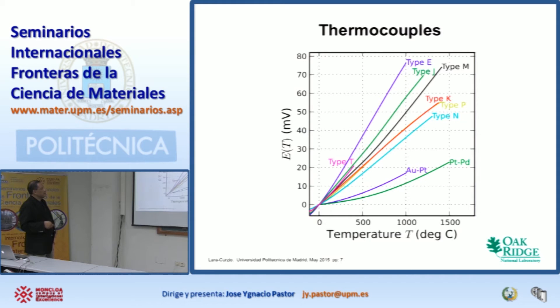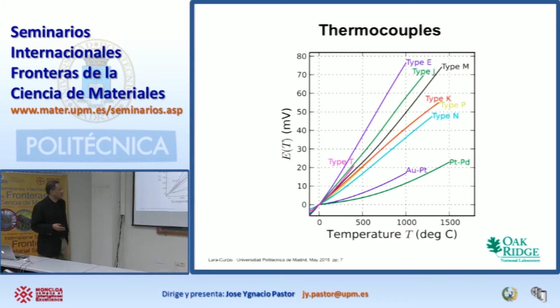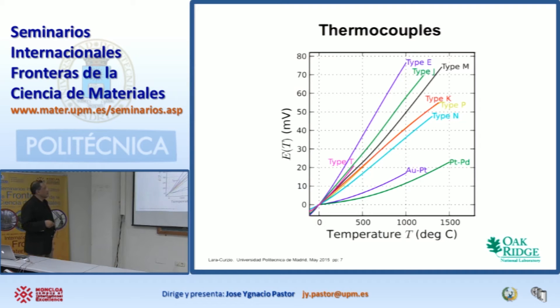We used to do a lot of work with ceramic matrix composites taken up to 1,600°C, so we used type S thermocouples — platinum with rhodium alloys. For many years this has been the standard way of measuring temperatures. When you select materials for your thermocouple, you want to make sure they are stable and will not oxidize, because if they oxidize the voltage you're measuring will be significantly affected. You also want to make sure the thermocouple is compatible with the material you are measuring so there are no chemical reactions. All of this derives from the work of Seebeck.